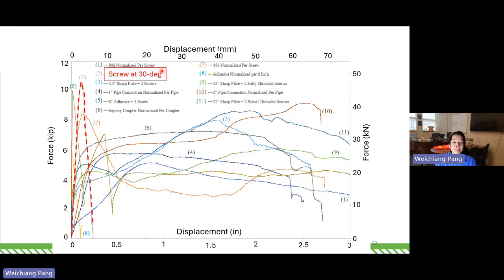For the same screw, if you put it at a 90-degree angle, or a 30-degree angle, an inclined angle, we also tested it at 45 degrees. At a 30-degree angle, you'll notice the initial stiffness is very high because the screw is in shear and in tension or compression, depending on how you load it, right at the beginning. So you have a very high stiffness. However, the drawback here is that it is less ductile. There's not much ductility you can get. The displacement level is pretty low before you lose all the load-carrying capacity. The strength is pretty high, okay?